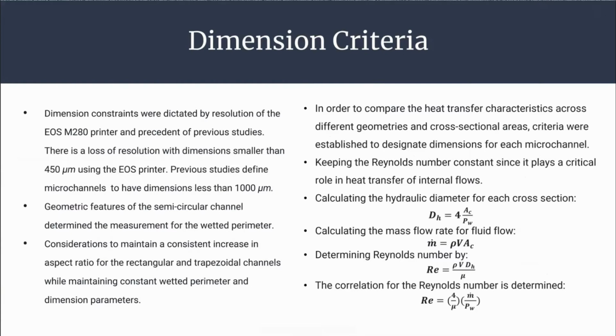We were initially given some constraints. One was based on the resolution of the EOS M280 printer, which is the metal 3D printer at the university. You lose resolution below a certain dimension size, and that was about 400 to 450 microns. Anything below that, you're not really going to wind up with a coherent shape. It's just going to be a blob. So that was the lower end of our dimension process. And then the higher end was 1,000 microns, established by previous studies that made the designation between what is a mini channel and what is a microchannel: being less than 1,000 microns.